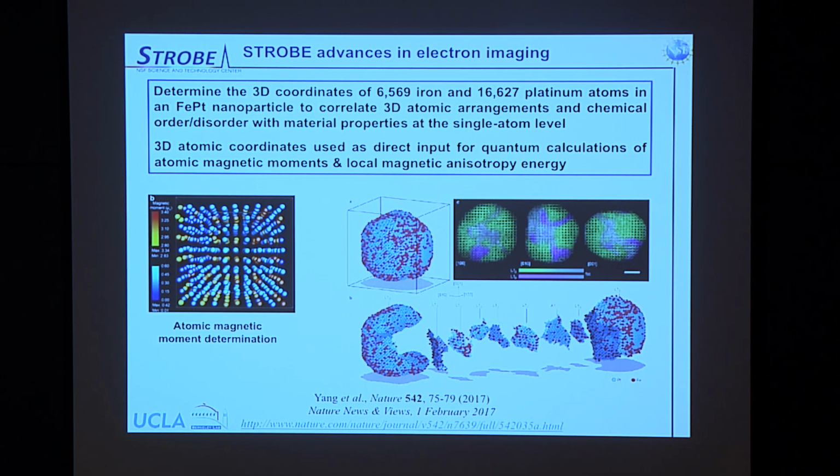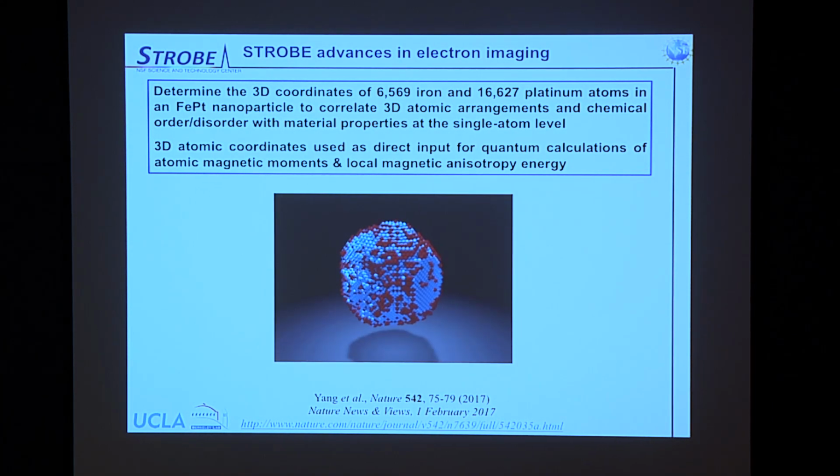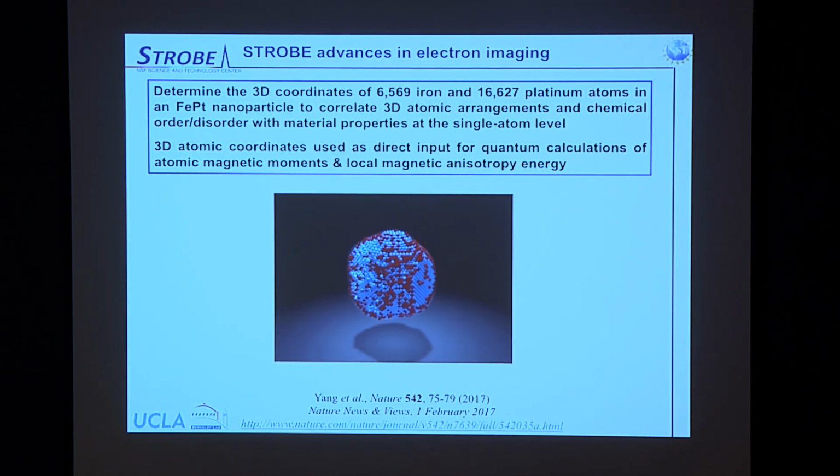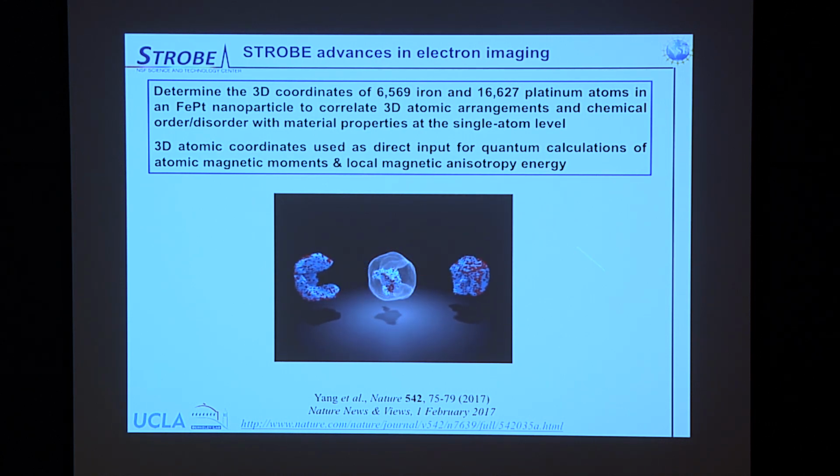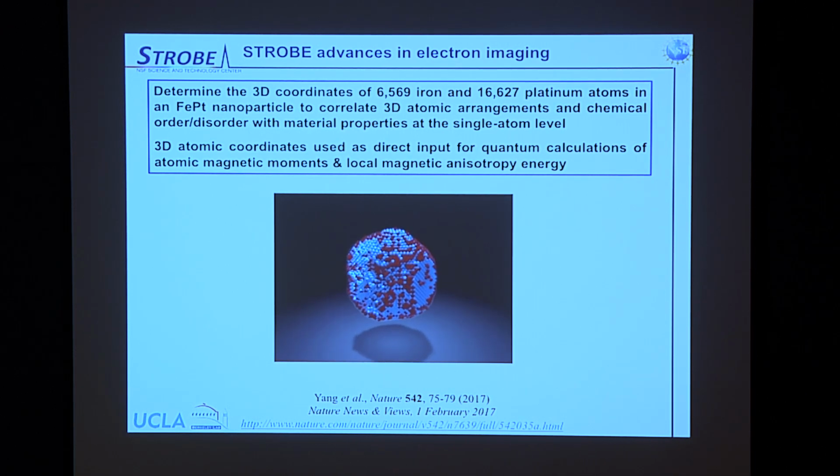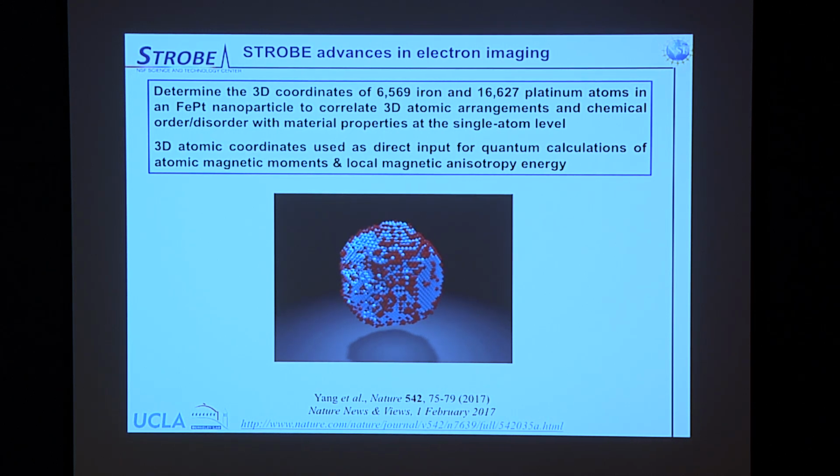When they made the electron image, and I wish this was from our microscope, but this is a simulation from the data. But this is what we want to be able to do in 10 years. Now they can take the 3D tomographic reconstructions and then pull apart the nanoparticle. And what they found was there were many different phases present in the same nanoparticle. Only one of them had the high magnetic anisotropy. And so that was why the material, everybody expected it to be great, but it wasn't. It was because there was not tight enough control over the synthesis.